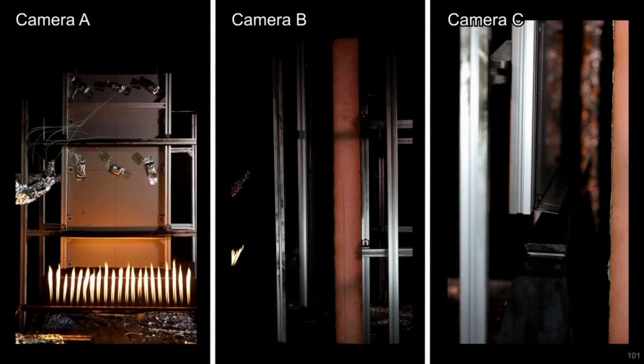Camera B, which is a bit dark admittedly in this view, shows the apparatus from the side. You can see the cut edge of the pink K15 insulation at the right-hand side of the camera B view. And camera C, also from the side, but in this case it's a close-up of the location where the burner is inserted into the panel joint. And again, you can see the insulation on the right-hand side. And you can see that the foil facer, if you look closely, is still there in this case.